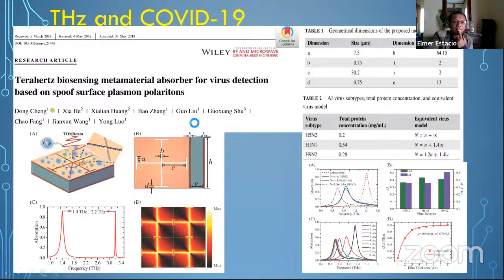It's titled Terahertz Biosensing Metamaterial Absorber for Virus Detection Based on Surface Spoof Plasmon Polaritons, pretty much what we are also doing with our spoof plasmon work. I can give you the dimensions here. These are in the order of several tens of microns, and they are able to fabricate this pattern here. Looks like a cross with these edges, and deposit it on some substrate, and they allow the terahertz beam to be incident in this direction and be transmitted.